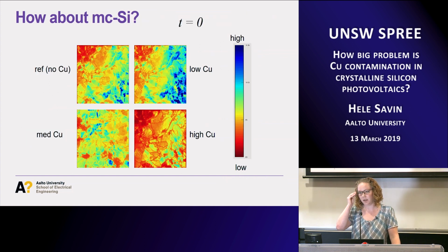In multi, things are a little bit more challenging, and you have to take some further things into account, but in principle it's possible. So we have done experiments where we intentionally contaminated different copper levels, so we are aware of how much copper we have. We have the reference, which we have tried to keep as clean as possible, then a little bit higher concentration and higher, and in the highest concentration we initially already start maybe seeing something. This is supposed to be close to the sister wafers.